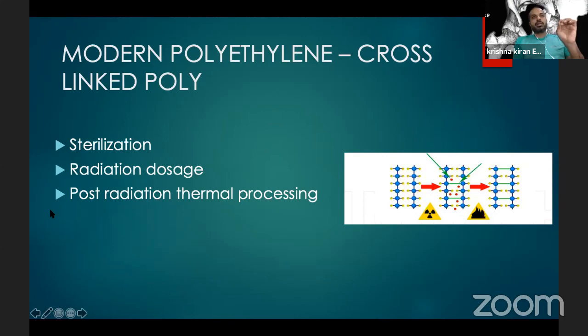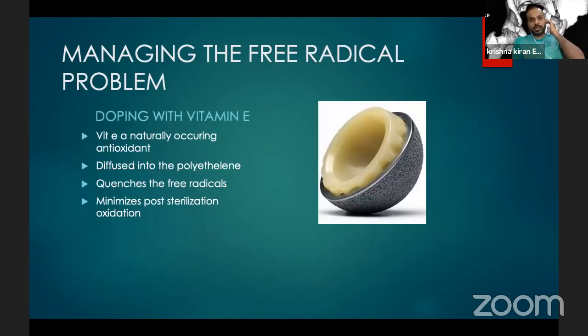The problem with cross-linking is that the mechanical properties are somewhat compromised. If you have an annealed polyethylene, you have more free radicals which are not taken care of because you have not melted that polyethylene. But if you have a remelted polyethylene, there are fewer free radicals and better wear properties, but the fatigue resistance of that particular polyethylene is slightly lower than an annealed poly. So whenever you're choosing a cross-linked poly, you must look at the radiation dosage which has been used, and what the post-radiation thermal processing was to take care of the free radical problem or oxidative damage which can happen with keeping that polyethylene on the shelf for a longer period of time.